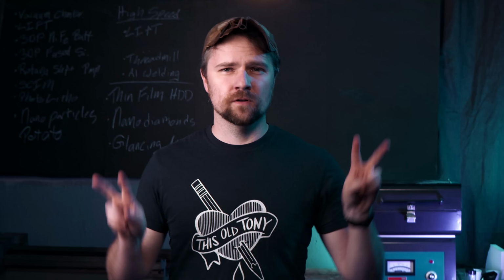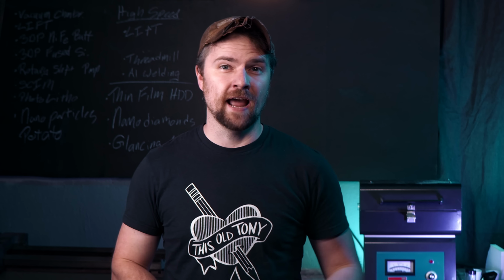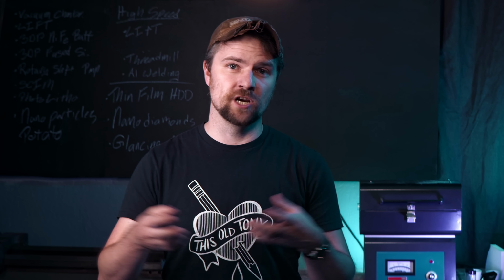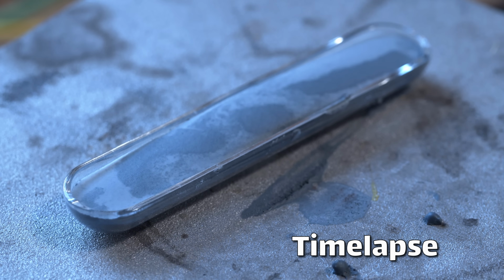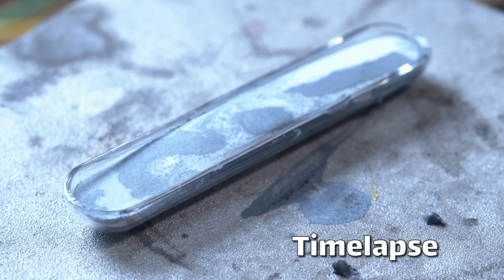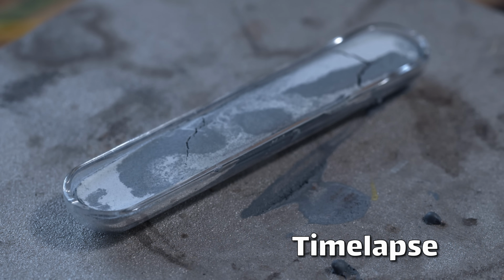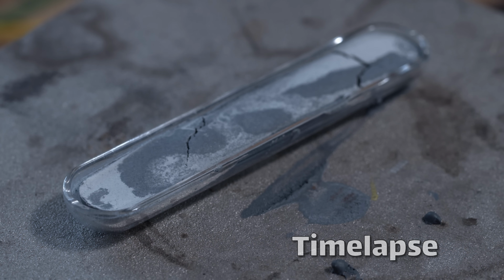The paper calls for aging the slurry in a drying oven for an hour, and the purpose of this is that the elevated temperature will make the cornstarch gel up. Just the same reason you use cornstarch in cooking to solidify dishes. The same thing happens here. So it makes the part become more solid, and in theory you can then demold that and put it into the furnace and you have the full complete part. I didn't find that to work at all.